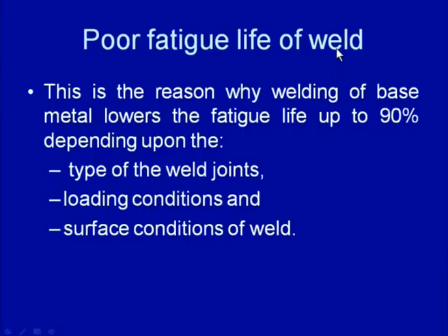For example, the tensile residual stresses will facilitate the crack nucleation stage if the external loading is tensile in nature, while the compressive residual stresses will discourage the crack nucleation stage under identical conditions. And because of the above reasons, as the weld joints in as-welded conditions have a lot of surface irregularities and discontinuities which act as stress raisers, and further these also have residual stresses, all these factors facilitate the easy nucleation of the crack under the fatigue conditions, and therefore,